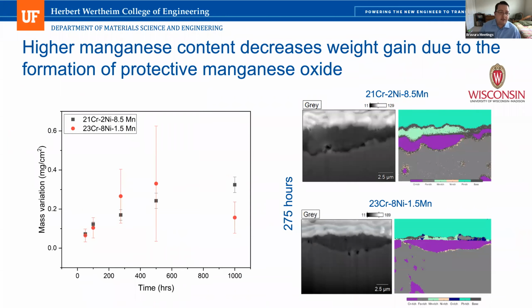Now, our preliminary results, we've completed testing all the way up to 1,000 hours on two different alloys, the 21-2N and the 23-8N alloys. And what we found to begin with is that the 23-8N, we see a lot more scatter in the results when we do multiple samples, and we're seeing just more oxidation in general. In addition, with the 21-2N, we're seeing much less oxidation and much less scatter.